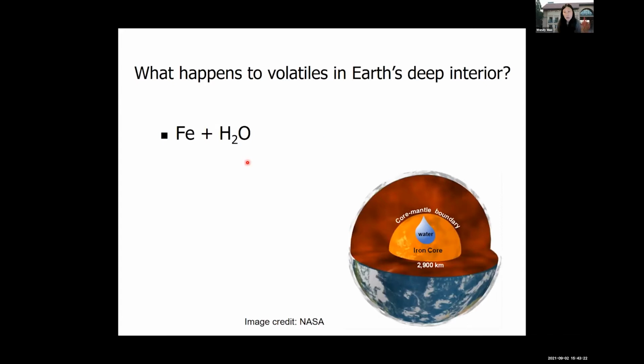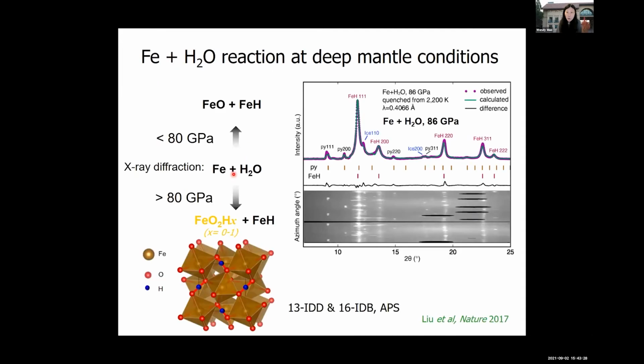So this is the example of what happens when you mix iron and water at high pressures and temperatures. A former postdoc in our group, Jin Liu, looked at iron plus water down to core-mantle boundary conditions. At more moderate pressures, below 80 GPa, in agreement with previous literature, he found that iron reacts with water to form wustite and iron hydride. But then at pressures greater than 80 GPa, there's an unexpected reaction between water and iron that occurred.